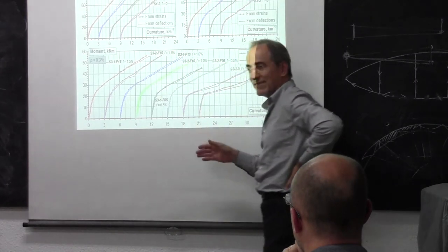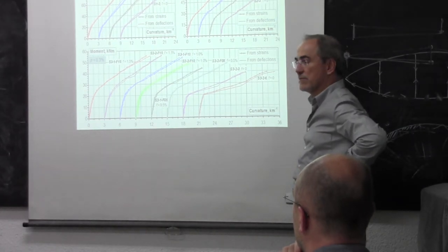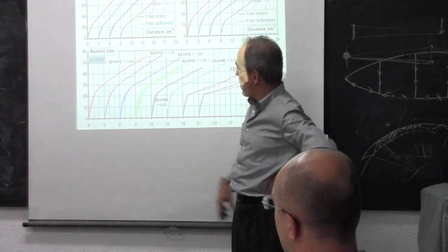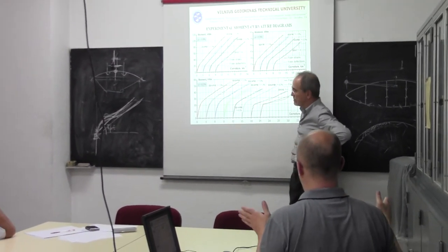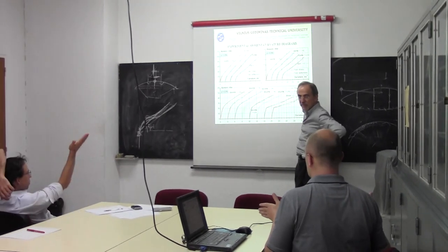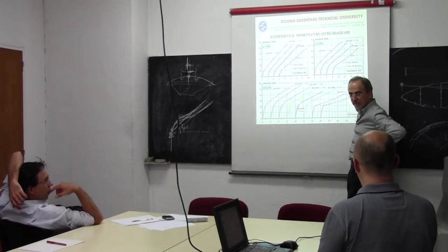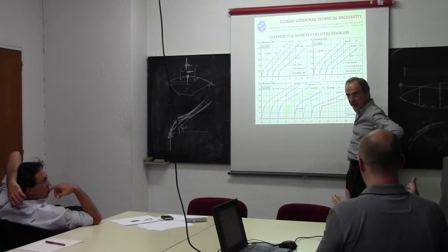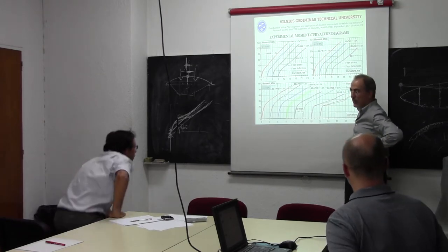So these are all 0.3. Lower due to fibers. I can say more. If we consider plates, slabs, with a small amount of reinforcement, where cracking is sudden, then the tension stiffening effect would be much more than this.